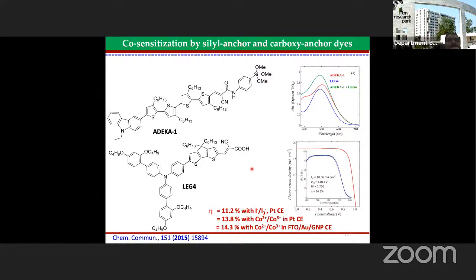This particular dye gave about 11.2% efficiency when you use iodine triiodide, and it has gone all the way to 14.3% when you use cobalt-based electrolyte and a gold-based and graphene nano platelet-based counter electrode. So you can see their corresponding absorption spectrum and also the IV performance here.